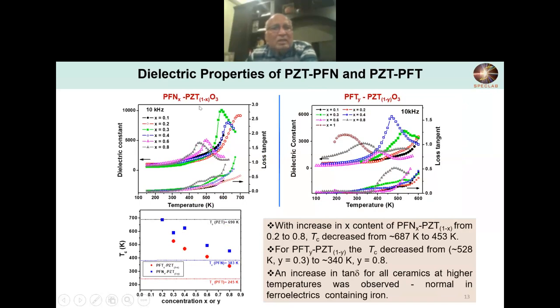We have studied, as a function of x, how the ferroelectric transition temperature changes. You can see that the maxima moves towards lower temperature as you increase the value of x. This is for PFN-PZT, and this is PFT-PZT. Similar things happen, and losses are still low, considered reasonable. So we have changes in the phase transition temperature as the x composition changes in both PFN-PZT and PFT-PZT.